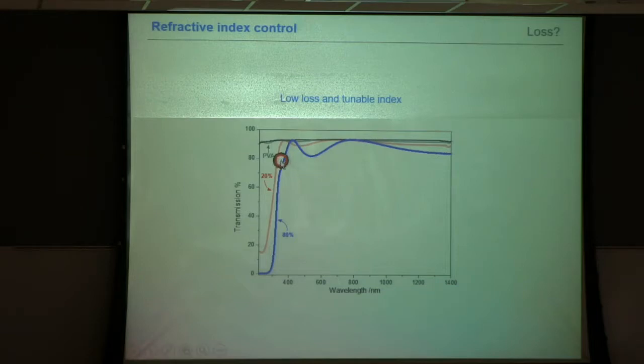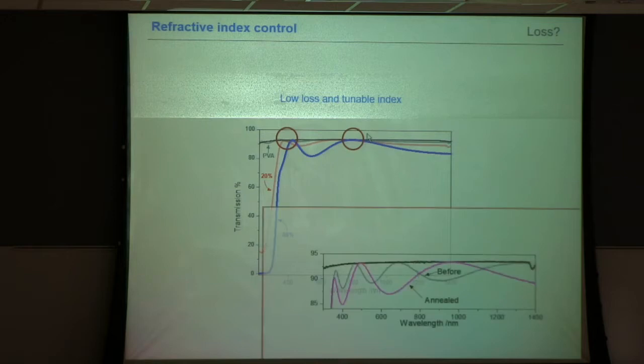So in our case, we looked at our polyvinyl alcohol here in gray, the glass substrate in black, and two hybrids, 20 and 80%. So you immediately see we have titanium in our films because the absorption of the titanium species comes in here. But more importantly, you see these oscillations increase when we increase the titanium content. That's actually what we really wanted to see. The maxima of the oscillations do hit our substrate transmission line. So it tells us we really have negligible absorption. And that even happens after annealing.